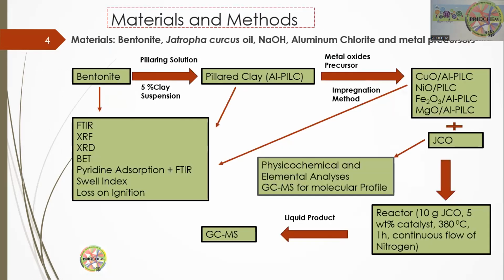This is the materials and method. Bentonite, the Jatropha curcas oil, sodium hydroxide, aluminum chloride, and all the metal precursors as nitrates. The bentonite will be converted into the pillared clay. We first prepare the pillaring solution, which is the reaction of NaOH and aluminum chloride, and then we mix it with 5% clay suspension. After the intercalation, we calcine at 500 degrees for 5 hours. We obtain the pillared clay.